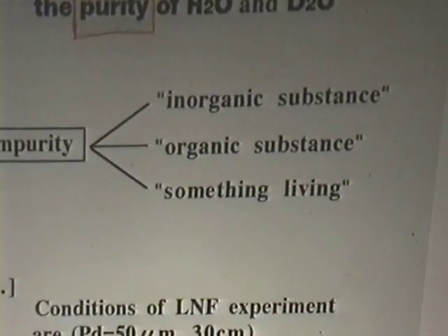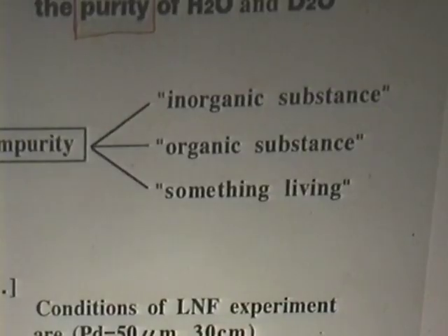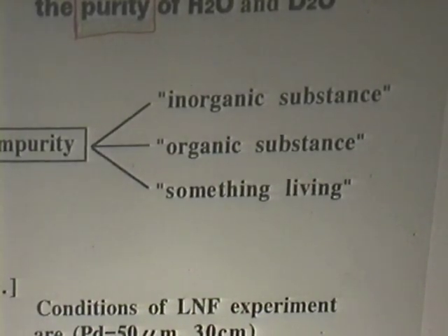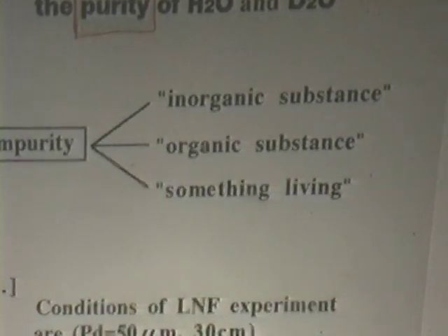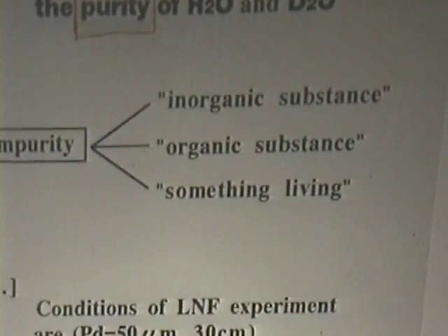I want to remember that in our experiment we have 55 moles of light water. The amount of hydrochloric acid is some 10^-5 mole, and the strontium some 10^-5 mole. So it means we add to the solution, in 1 liter of solution, 1 milligram of strontium. 1 milligram, almost nothing. And the anti-cracking agent, the mercury, is 10 times lower, 10^-6. Really ultra pure water.